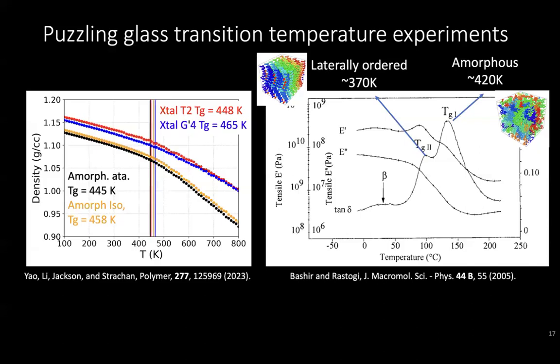And so we decided to do some simulations, okay? So we built amorphous PAN with many papers, lots of experience doing these type of simulations. You heat it up, you equilibrate it at high temperature, you cool it down, and you see this change in slope. That's the glass transition temperature. If you compare that value with the experiment, you need to be about 30 degrees higher than the experiment because our cooling rates are 10 orders of magnitude faster than experiments, okay? So if you ever see an MD simulation and they predict the glass transition temperature right on, they're wrong. You have to be higher because you're doing 10 orders of magnitude faster cooling. All right, so we understand that very well.